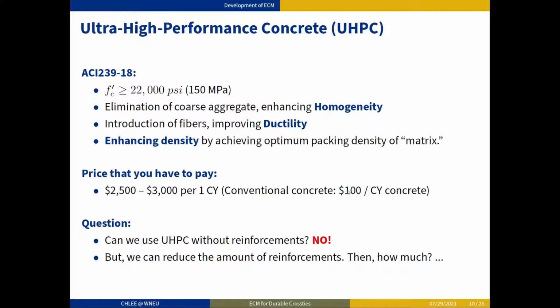If you first take a look at the UHPC, the definition of the UHPC is ambiguous so far. However, ACI 239 provides a little bit more specifics. For example, the strength must be greater than or equal to 22,000 psi, in SI units about 150 megapascal. Also, ACI 239 said the UHPC has no coarse aggregates to enhance homogeneity, and introduces fibers for improving ductility and enhancing density by achieving optimum packing density of the matrices.